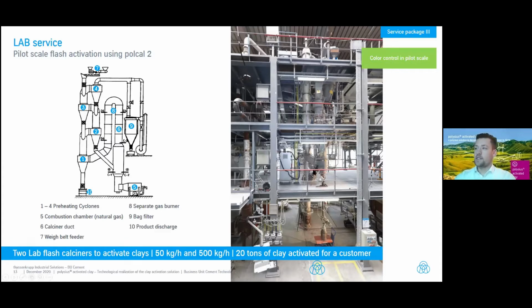With this facility here, we are able to produce around 50 kilograms per hour. So this is not to produce lots of material, but it is to show the feasibility of the process. If we want to produce more activated clay, we are going to the second device, which is outside this building. And there we can produce around 500 kg per hour, which we also did for a European customer where we treated 20 tons of material and activated it.